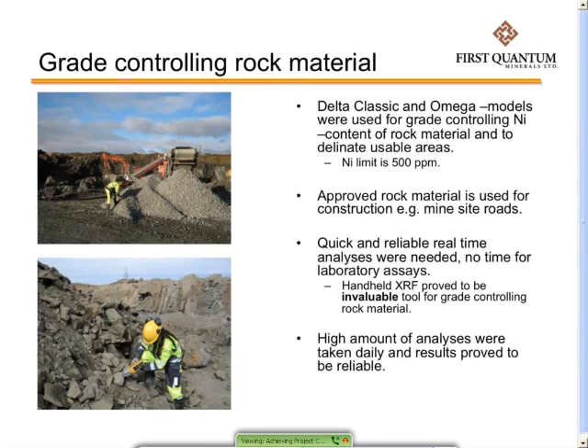In controlling grade during initial ramp-up, nickel had to be below 500 parts per million to be used on mine site roads. Such was the speed of the stripping and need for rapid decision-making regarding placement of stripped material, the Delta Classic and the Omega became a frontline tool.